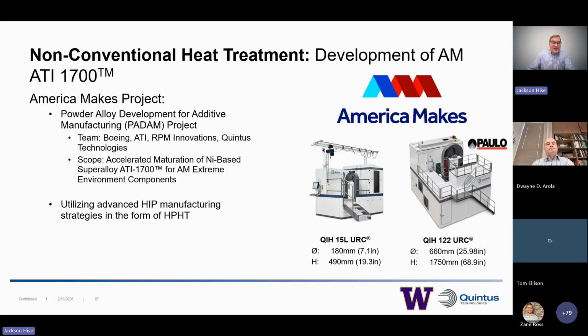I talked about something that's been standardized, such as Ti-6Al-4V, but there's also plenty of work going on to optimize and develop these optimized parameters for other materials. One of this work is with America Makes ATI 1700, where we're working with Boeing, ATI, and RPM Innovations to accelerate the maturation of the nickel-based superalloy ATI 1700. Here at Quintus, we're taking part in this by utilizing advanced HIP manufacturing strategies in the form of high-pressure heat treatment to optimize the microstructure for our desired outcome.